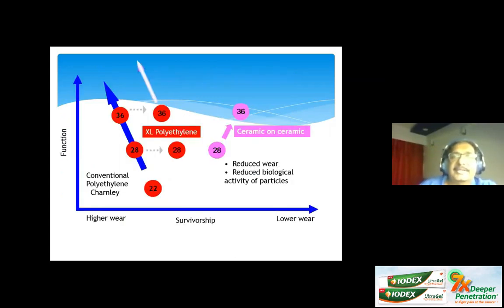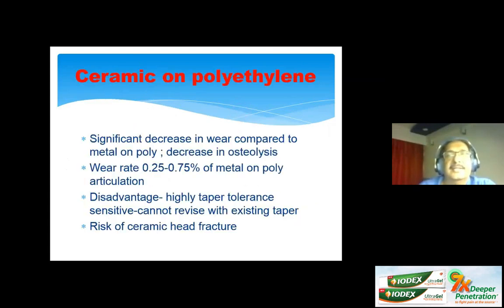So ceramic on ceramic certainly allowed us to move on the graph towards the lower wear scenario with improved function, reduced wear, and reduced biological activity of the particles. So ceramic on polyethylene is certainly what we are using now more and more, all throughout the world. There is a significant decrease in the wear compared to metal on poly. Wear rates are about 0.75% of metal on poly. The disadvantage being that the taper tolerance is very sensitive and you cannot revise with an existing taper. There is always a small risk of a ceramic head fracture.